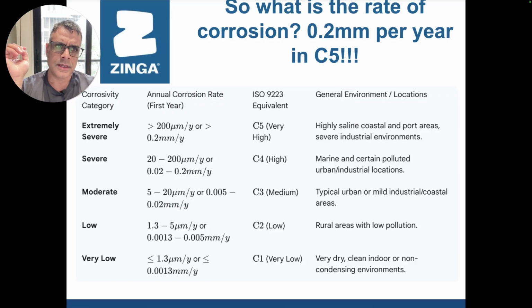So coming back to this, in C5, when we say 200 microns is 0.2 mm, 1000 microns makes 1 mm. So if your steel is going to corrode at 0.2 mm per year, that means you're losing 1 mm thickness every 5 years. If it's, let's say, a 6 mm plate, then it's definitely going to eat through, and corrosion accelerates as the thickness keeps going down. In the extremely severe category, where you're losing 0.2 mm per year, it is usually saline, coastal and port areas and very industrial environments. You lose 0.02 to 0.2 mm per year in a marine and polluted urban industrial location, and it goes down. But the idea is that our solar structures are always installed at places where normal human life is not really happening.